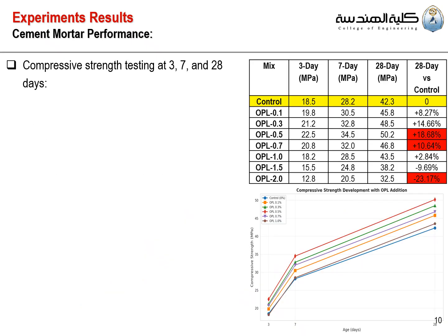For this slide and the next slide, we will present the strength testing performance for the OPL modified cement mortar. We will start with the compressive strength testing. We did it for all mixes at all curing ages, 3, 7, and 28 days. And as you can see from the table, the control mortar has typical compressive strength. We have 18.5 megapascal at 3 days, 28.2 megapascal at 7 days, and 42.3 megapascal at 28 days.